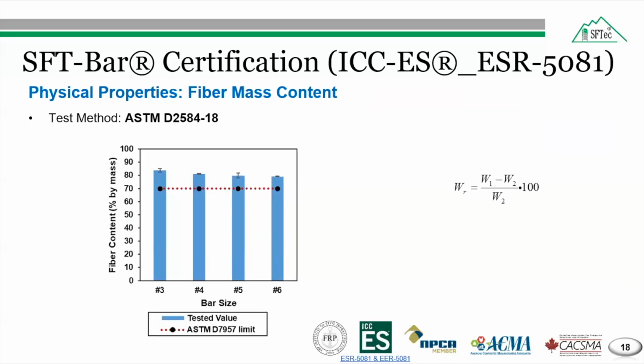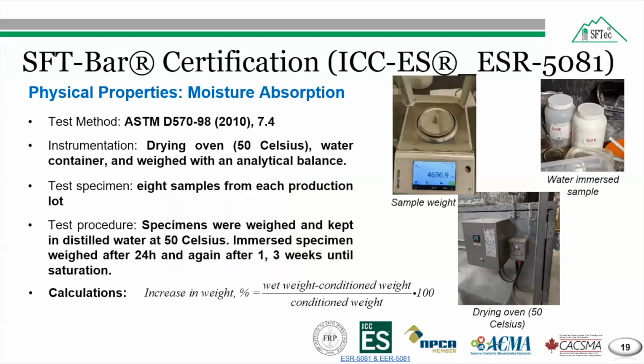And for the tested glass fiber reinforced polymer bar, the SFT-Bar, the average fiber content was found to be higher than 70%, which is required in ASTM D7957. The moisture absorption test is important, and it aims to prevent excessive moisture absorption that can weaken the bar. It also tells us what kind of resin is used in our bar, whether vinyl ester or polyester. So it is an important test to distinguish the type of resin matrix.